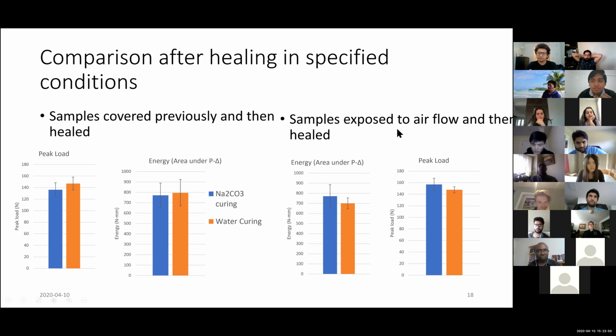And in terms of samples which were exposed to airflow earlier and then were healed, we can see that the sodium carbonate curing is performing better for energy as well as for peak load. In terms of concrete cylinders, we observed that even without damage, sodium carbonate curing was performing better. But in these cases, the difference was not as much, since if I cure the samples from outside and let the ions flow to the bond, then there is very little chance of ions getting through to the bond and then reacting and precipitating something. So that is why the difference in bond strength was not as stark as the difference in compressive or split tensile strength. But we can see that sodium carbonate, if it's introduced in a sample which has been exposed to this airflow or shrinkage or some form of damage, performs slightly better.